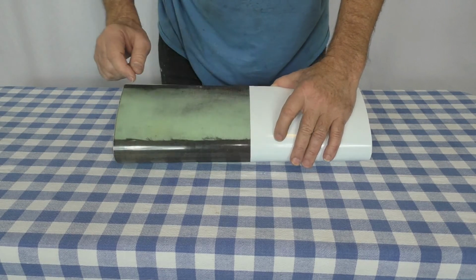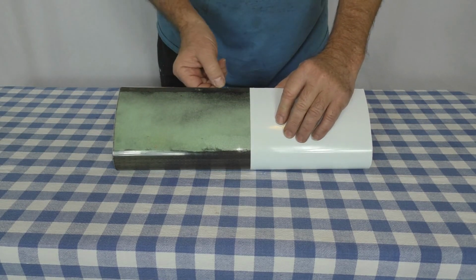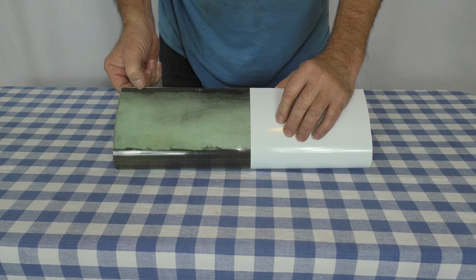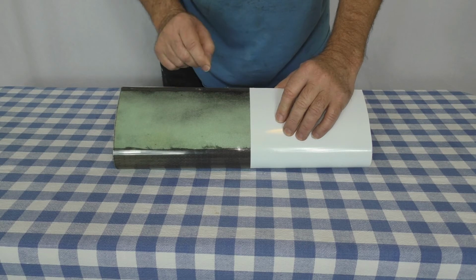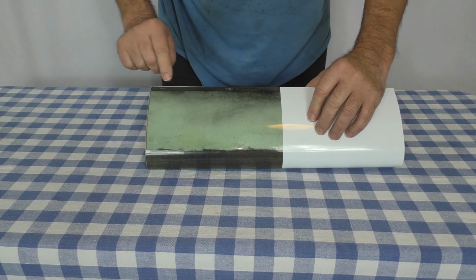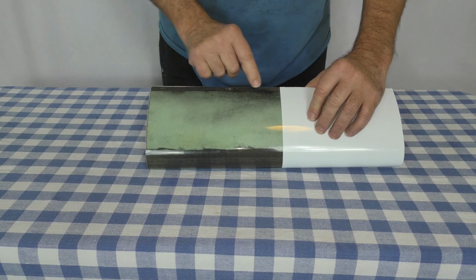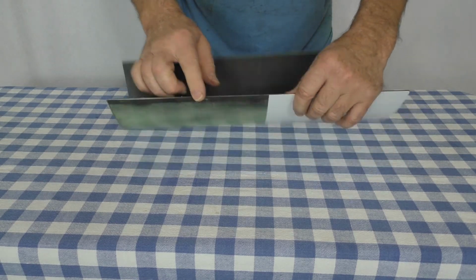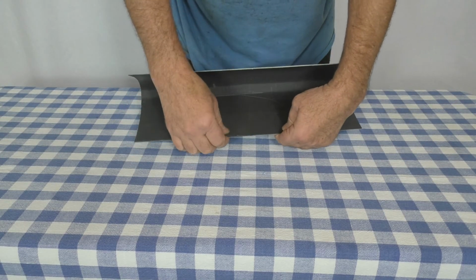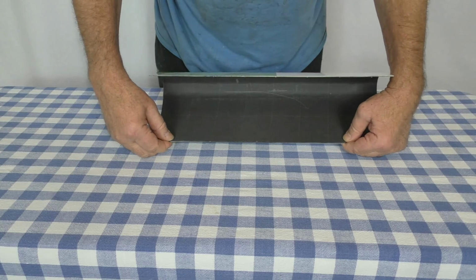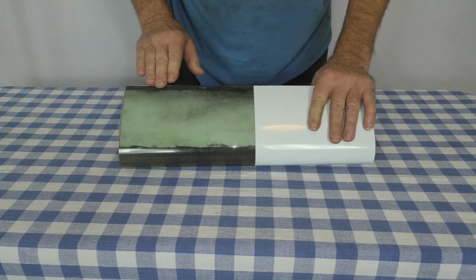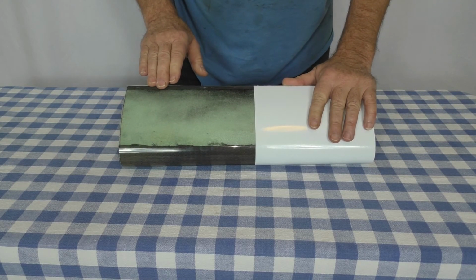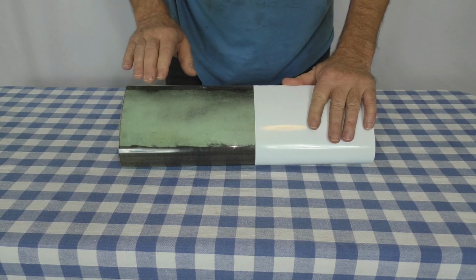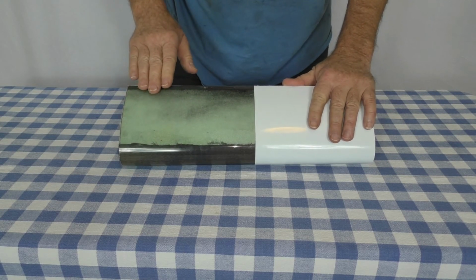So that's an issue. And then here, where I put in the unidirectional pultruded carbon fiber rods, the rectangular ones here, I have a series of small spots where it's not bonded well. This is true on the outside and on the inside, and it's quite bumpy on the inside. It was very, very difficult.